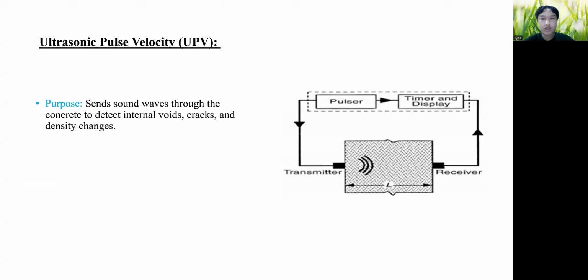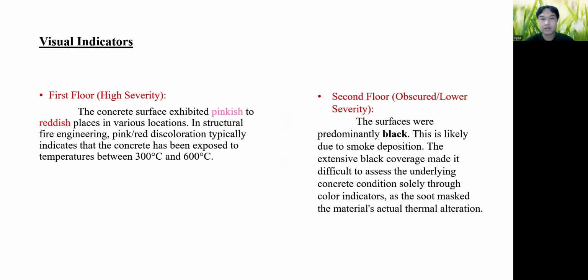Ultrasonic pulse velocity: the main purpose is to send sound waves through the concrete to detect if there are internal voids, cracks, or density changes. So the visual indicators. There are two floors in this building. The first floor is highly severe. The concrete surface is a bit pinkish in color, and in some places it gives reddish colors. These pinkish and reddish colors typically mean that the concrete has been exposed to temperatures between 300 and 600 degrees Celsius, which is really hot.